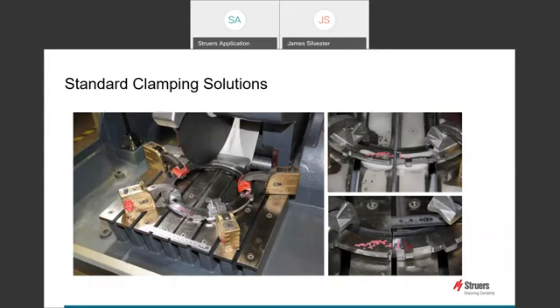So if we look at our first example, it looks fairly simple. It's just a ring that we're trying to cut. But even simple-looking cutting actions can sometimes need specialist clamping solutions. This large steel ring needed a sample cutting from a specified location around the circumference. However, whenever the first cut was almost complete, the internal stresses would collapse the ring on itself and grab the cutting wheel, causing the wheel to break. The image on the right clearly shows the challenge when cutting such a workpiece.